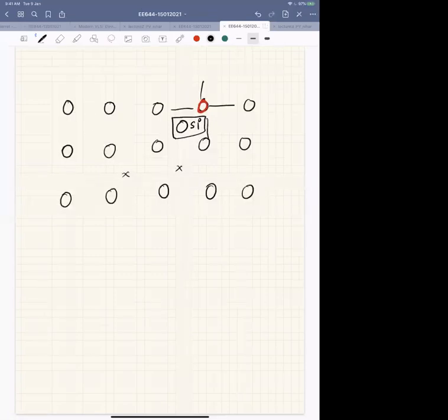So in this case, these atoms will basically create a hindrance for the movement. Because they could move, actually, they do move, and there is a technique we call gettering in fabrication. So we just remove these. They are inactive, right? Since these are not charged and not active, they are very inactive. But sometimes they may create issues, so they are removed from the active area of the device by the process we call gettering, right? So this oxygen is still there, but it is inactive, right?